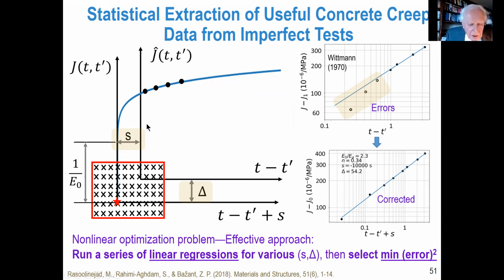That's very, very, very fast. So what we did, we do sampling and search. We assume all these combinations shown here. There are actually 60 combinations. We run linear regressions for all of them, then calculate the coefficient of variation square for each linear regression, and see which point minimizes it. This red point here minimizes that and gives the values. And this is very fast, even with these linear regressions, it's a fraction of a second to get the whole fit.